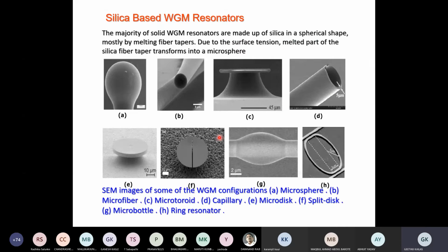So usually the WGM resonators are made of silica. The majority of solid WGM resonators are made up of silica in a spherical shape, mostly by melting fiber tapers. Due to the surface tension, the melted part of the silica fiber taper forms into a microsphere. So you imagine an optical fiber, and the end of the optical fiber is melted, and usually it forms a spherical shape. And this sphere can very well act as a WGM cavity. Okay, and if you dope this one with some gain medium, it can also act as a WGM laser.